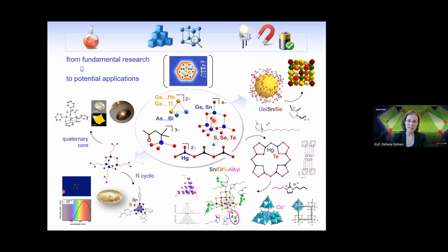If you go to this side, then you will go to these ionothermal reactions, which require a little bit of temperature, not too much, but maybe 80 degrees, and you have to use sealed ampules. So it's a little bit more complicated. And the most challenging kind of synthesis is certainly for these metal-like compounds, since you can guess that a metal doesn't want to be in a negative oxidation state. And once you force it to have a negative oxidation state, it wants to get back. So you will have to take great care of no oxygen being around, no water being around. These have to be strictly inert conditions. We use glove box techniques, we use Schlenk line techniques, and with this, it's very easy to do, but you have to be trained in this technique.